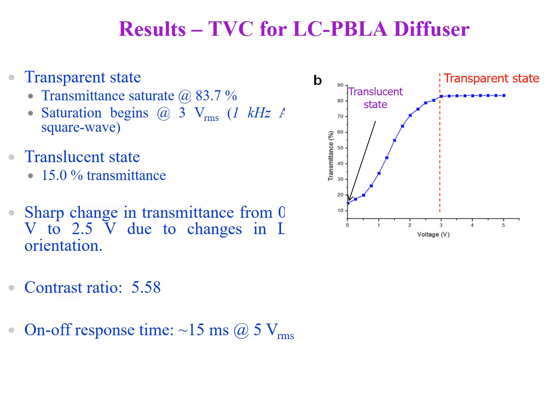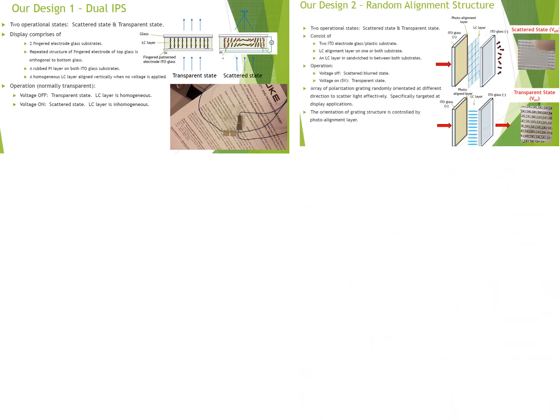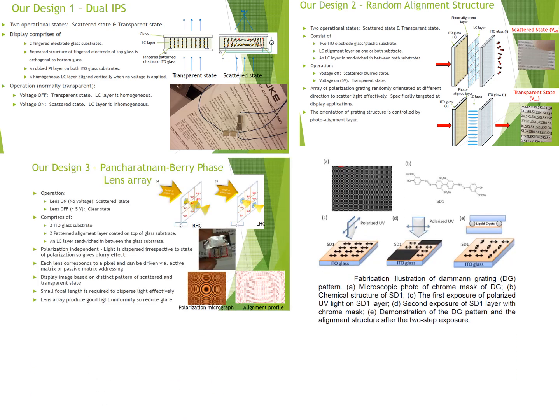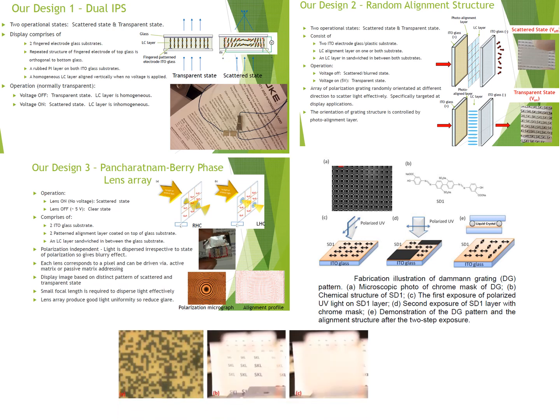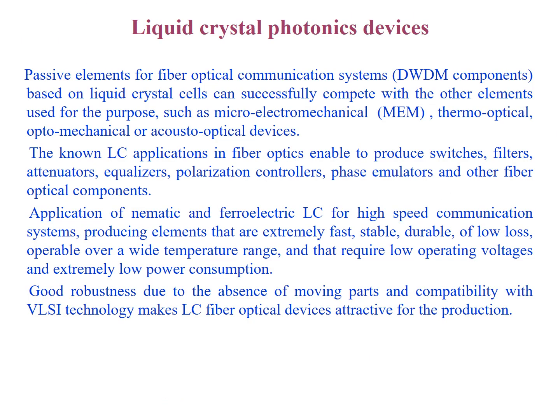For instance, we can see that the contrast ratio can be extremely high, and we can change the transmittance from opaque to transparent. We put our scattering structure not in the bulk but on the surface of the liquid crystal. We can use different designs: in-plane switching, random alignment structure, PB phase lens array, and so on. So this picture is much better because there is no degradation of the liquid crystal, and you will have the same excellent smart window effect.